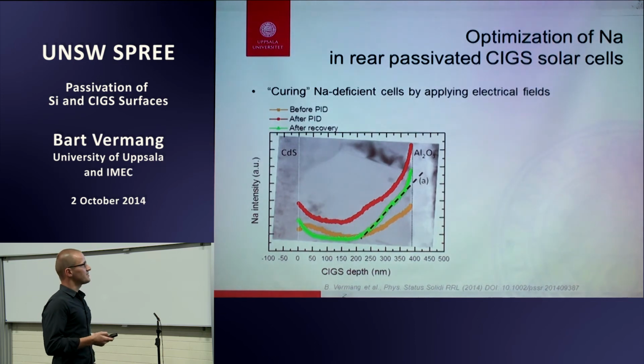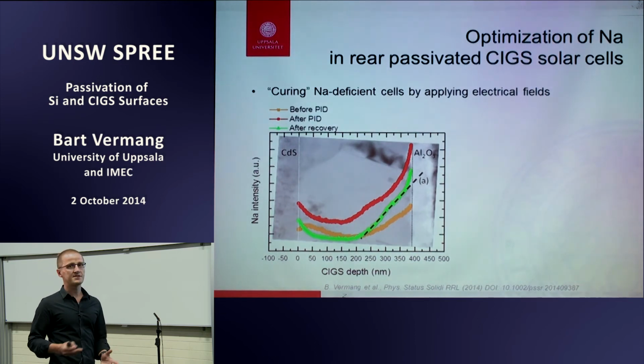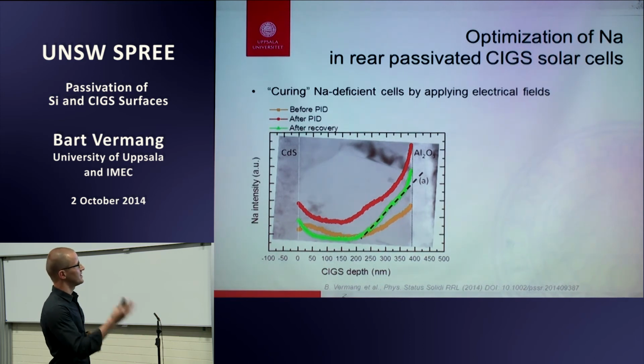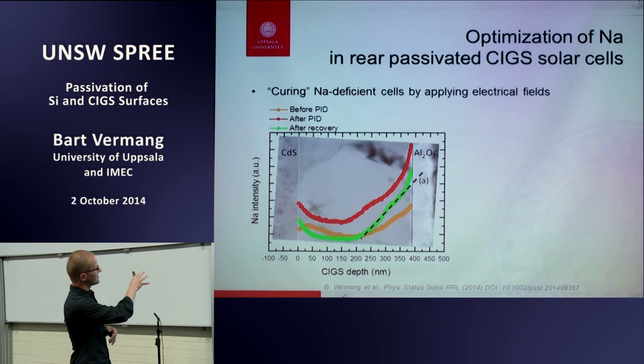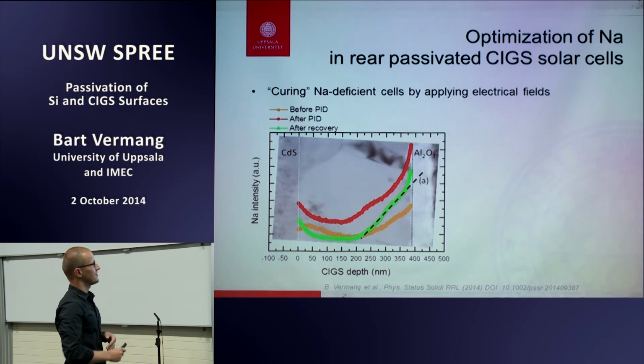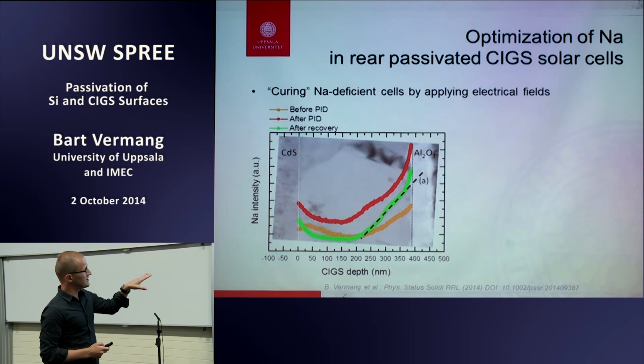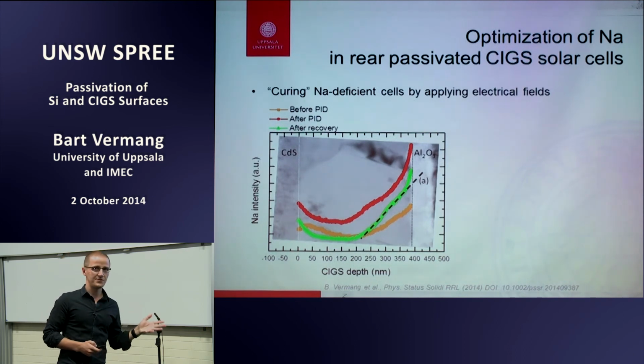But one of the disadvantages, like I mentioned in the beginning, is that the aluminum oxide layer itself is a barrier for sodium diffusion from the substrate into the CIGS layer. So here you see a SEM picture with the cadmium sulfide layer, CIGS in the middle, and the aluminum oxide layer at the right. And then we measured the sodium content within the CIGS layer at 3 different moments. In orange, we have it as deposited. And you see, we know at that moment we have sodium deficiency. We have very low fill factors.